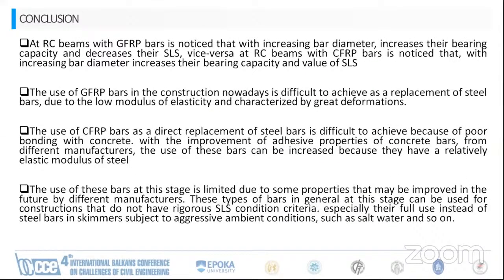Finally, conclusions. At RC beams with GFRP bars is noticed that with increasing bar diameter increases their bearing capacity and decreases their SLS. Vice versa, at RC beams with CFRP bars is noticed that with increasing bar diameter increases their bearing capacity and the value of SLS. The use of GFRP bars in construction nowadays is difficult to achieve as a replacement of steel bars due to the low modulus of elasticity and characterization by great deformations.